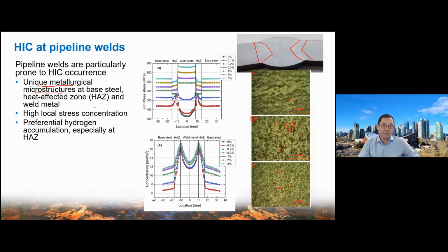At the same time, the welding area also has local high stress concentration. So we just used a model to simulate. At the HAZ, you can see the stress has a peak in this area that's associated with the stress concentration.